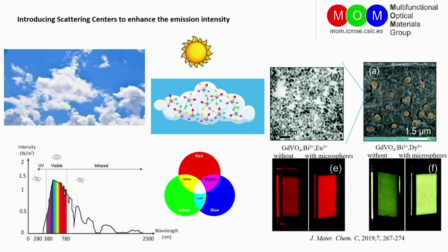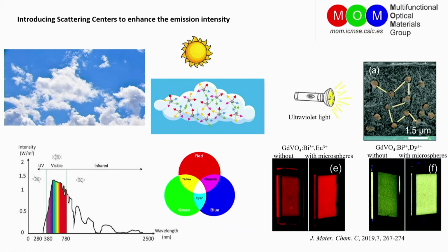So in our group, we also introduce scattering centers in the system, but in a controlled way, in order to enhance the intensities of phosphor particles. For instance, titanium oxide microspheres are added in the layers of phosphor particles. Under illumination, the microspheres will scatter the excitation light, increasing the time for excitation light traveling inside the layers. This increases the possibility for excitation light to be absorbed, thus enhancing the emissions. The photos clearly confirm that the introduction of scattering centers can enhance the emission intensities of phosphor particles.